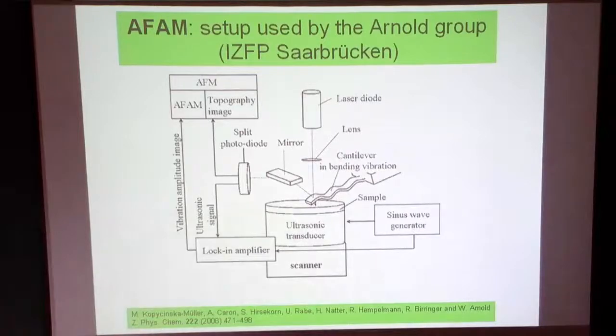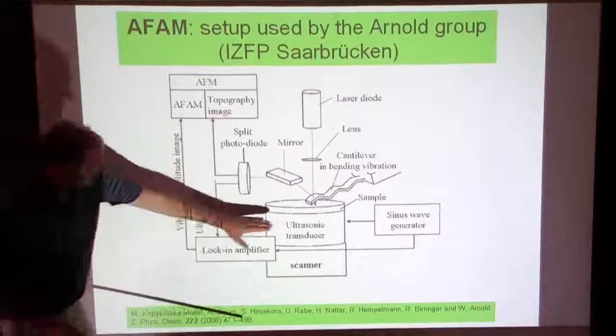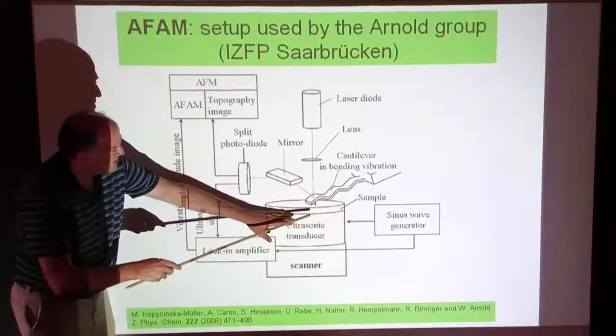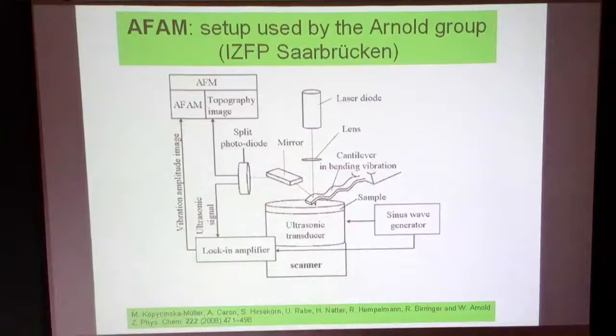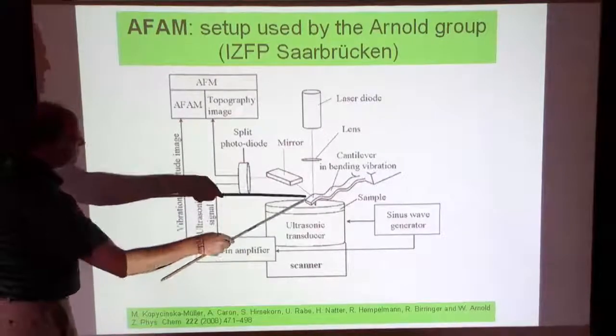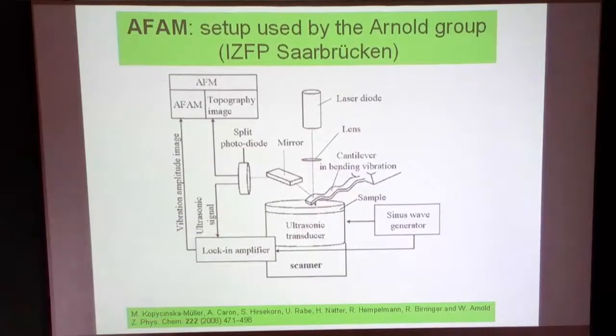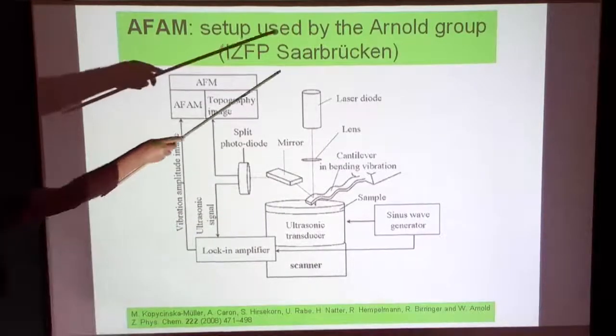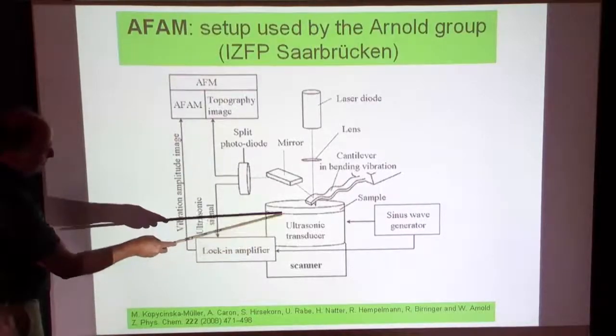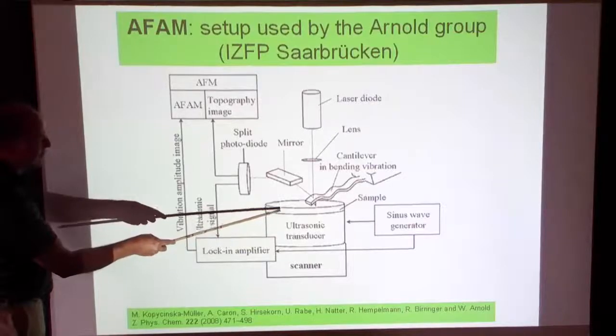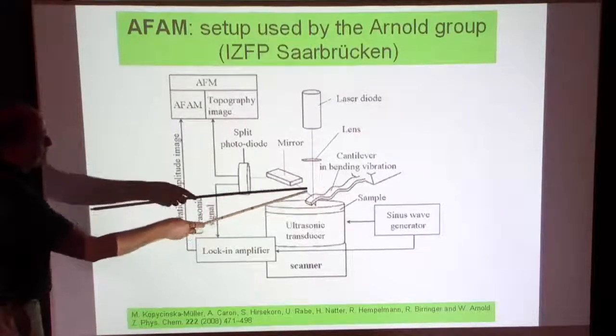And I showed some of the data already a couple of years ago. This is what we call the AFAM, the acoustic atomic force microscopy. If you forget the lower part here, you just have a sample, a cantilever which has a certain tip. The tip is in contact with the sample. That's a normal atomic force microscope. It tests the surface, the roughness of the surface, asperities or whatever, surface friction can be measured that way, and many other things, magnetic forces, van der Waals forces. That's a wide variety of this technique. It works with the recoupling of that system to a mirror and to the photodiode and so on. You know that. We added to that, with the help of Walter Arnold's group in Saarbrücken, an ultrasonic transducer underneath. We excite the sample in a certain way and then look for the bending vibrations of this cantilever.